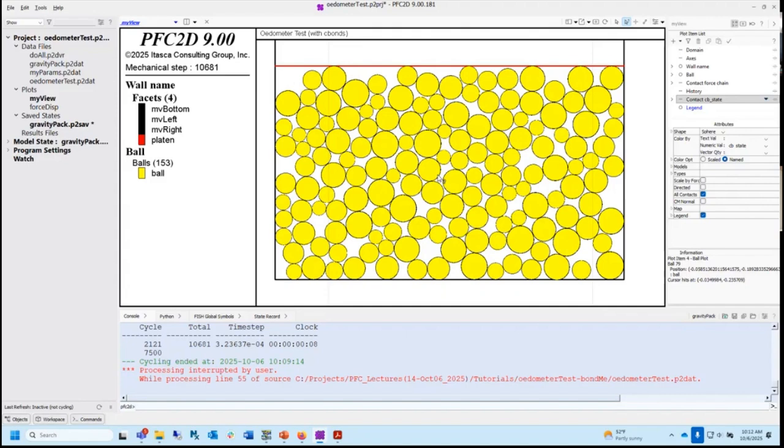So it would be like sandstone. You could see how this would happen. Imagine you do a test. You put dry sand in, fill it, let it sit there, and put in bonds where it's touching. Maybe you could heat it and they would weld together, and only the particles that were touching would weld. But then run your odometer test for a while. Now you have a much more packed system with a lot more contacts. Now heat it, and you're going to get a much denser amount of bonds. That's going to be stiffer and stronger.